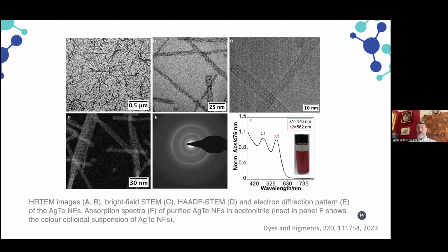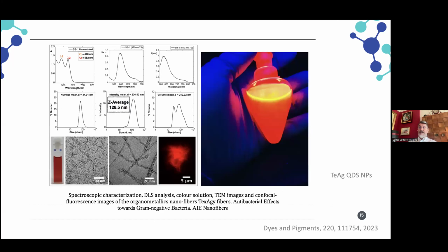For us, this was a problem, because if you would like to use this material for imaging, you cannot see absolutely nothing. So we decided to modulate the properties of these materials in order to check what happened when the silver is also reduced. And here we have the results. When we reduce the silver in the complex of the materials to silver nanoparticles, the solution becomes more red and then highly emissive. In the solid state, the fibers are strongly emissive, and in solution, the emission in concentrated solution is yellow, and the emission in more diluted solution is completely red.